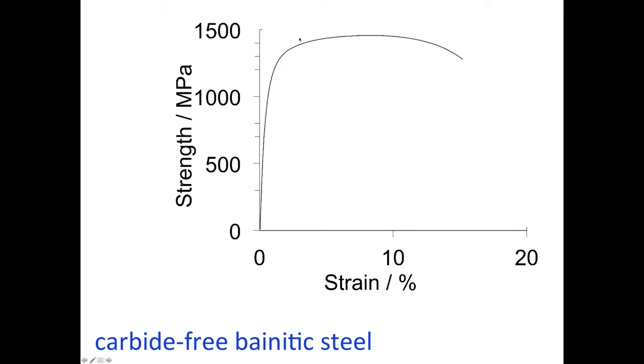We have a strength of the order of 1500 megapascals and an elongation of the order of 15%. So the domains we have identified, where transformation and production conditions are appropriate, can result in very rapid design of a steel. It's when we deviate from those domains that it becomes impossible to obtain fully bainitic steels.